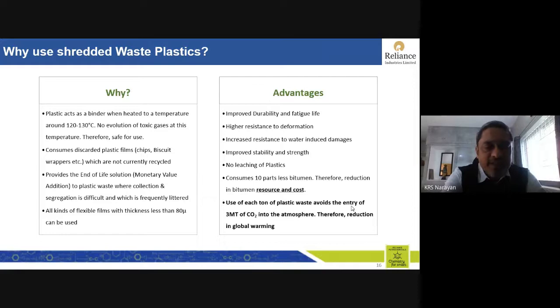So all types of flexible films with thickness less than 80 microns can be used, as per the government policy. All types of packaging materials, multi-layer packagings, are less than 100 microns. 80 microns is an average one which you can pick up. Advantages: you can improve the quality of the road, durability and fatigue life of the road. It has higher resistance to deformation, and resistance to water-induced damages, because the plastic coating on the aggregates would provide a water barrier from entering the pores or the spaces between the aggregates as well as the material. Improved stability and strength.